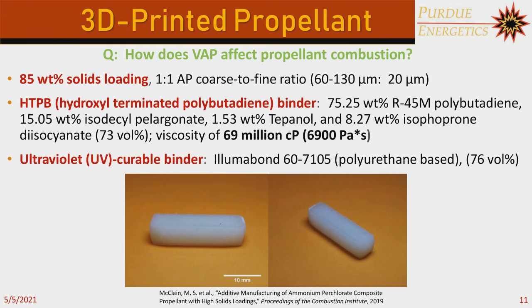In this particular study, we used 2 different propellant mixtures. The only difference here is we used 2 different binders. The solids loading of ammonium perchlorate stayed the same, essentially. The first binder we used was HTPB, which is a very common traditional solid rocket binder that thermally cross-links, and it takes a while to thermally cross-link, so it's a pretty slow process, and that can lead to propellant deformation. The other one that we used was a UV curable epoxy, and the idea behind this is to very quickly cure your propellant into its shape so it doesn't deform too much.